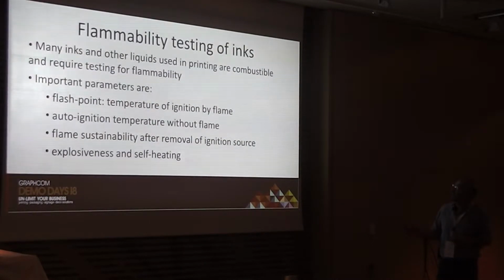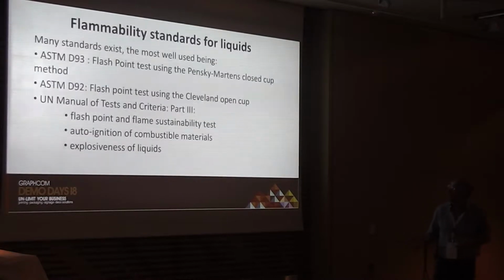And that's flammability testing of inks. Okay, inks on their own, they usually are tested, they're given a certificate with it. Some people actually ask me, I've got this ink, it doesn't have a certificate, or the certificate is from a country that's not fully accepted in Europe. Is it possible to get a test done on this? And we do flash point recognition, we do a lot of these things. These are United Nations tests, by the way, and United Nations tests are independent of the ISO test. So even if you do have an ISO certificate, the United Nations regulations for transporting expect you to have the test reports as well.